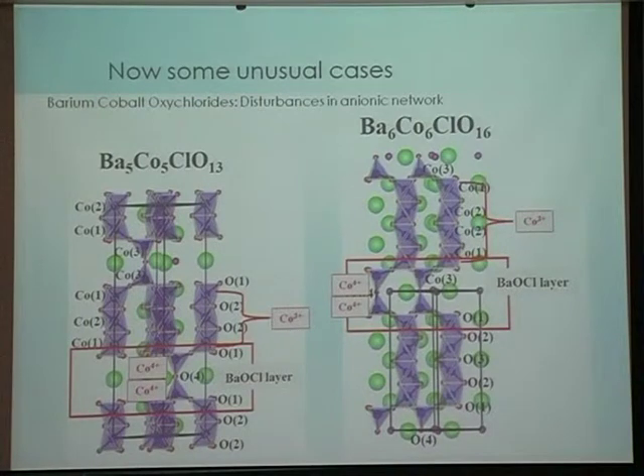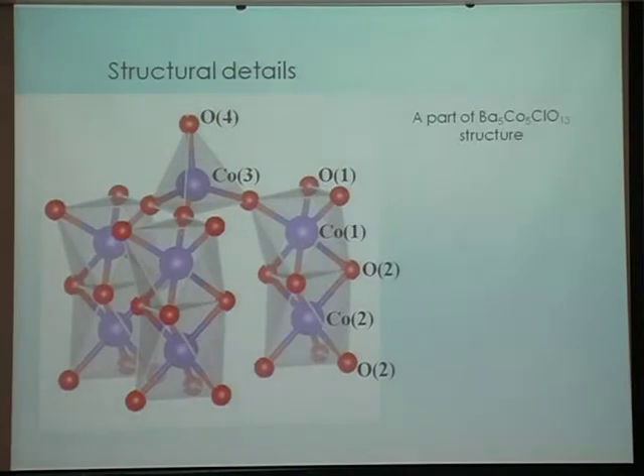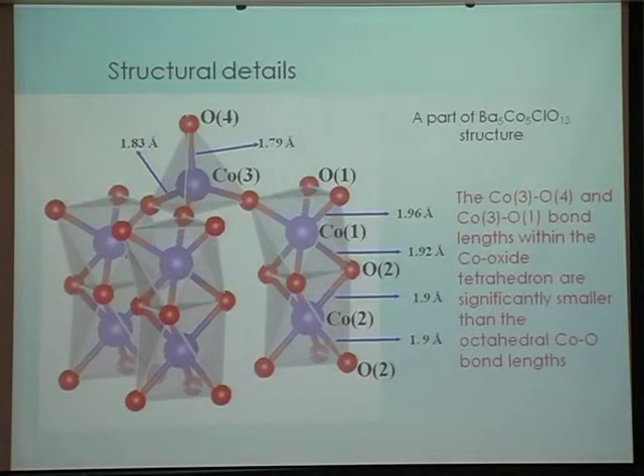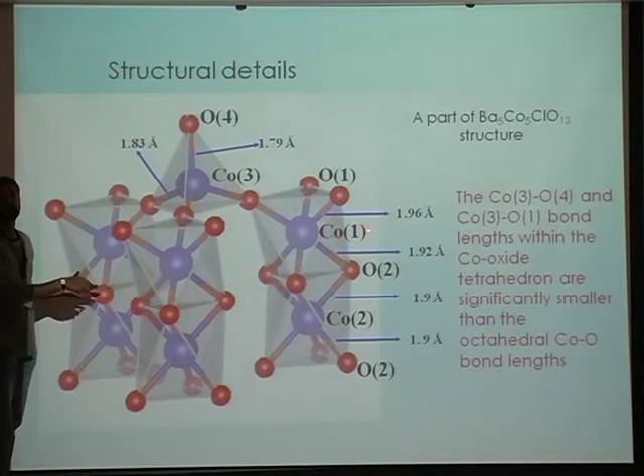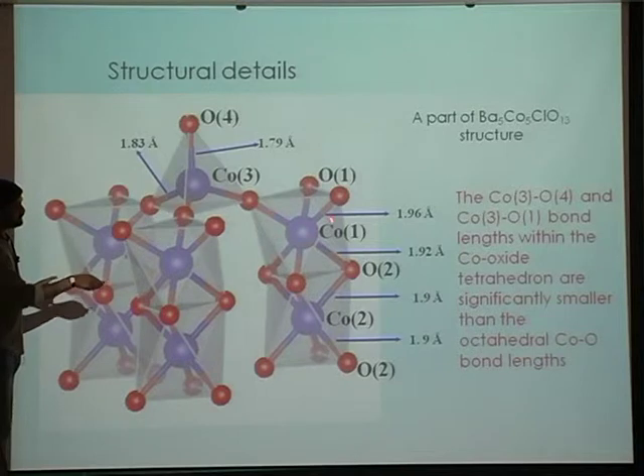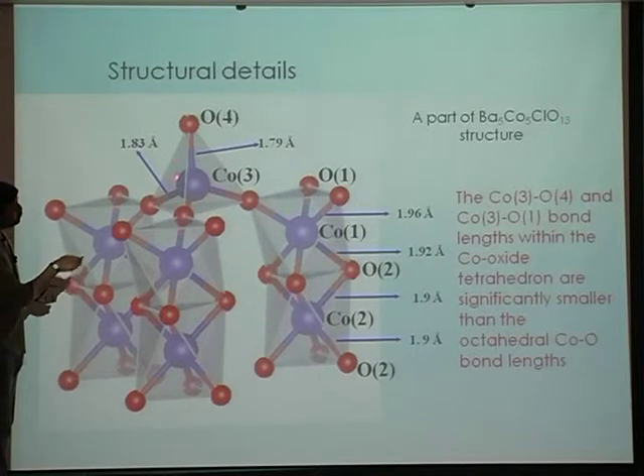Now what I'll try to show you is a small piece from here and try to draw your attention to this. It is the same thing that I have shown before, but only a couple of octahedra shown sharing a face connected to a tetrahedra. Of course, there are other tetrahedra here and other octahedrons here, but forget about them. So that's an expanded view of a part of the lattice. The interesting part is, I would ask you to look at the bond lengths. This I note as cobalt 1. There are 3 types of cobalt in this particular case. This is cobalt 1, this is cobalt 2, and this I call cobalt 3.